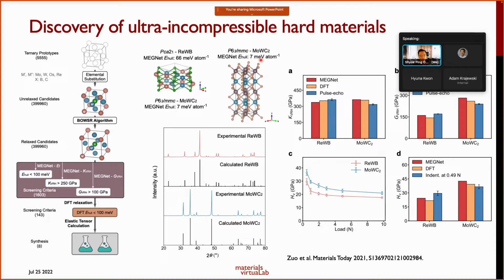Now, even with such a simple concept, we can already apply that to materials discovery. So I'm going to show you an example here, which is, I would say, one of the few examples where we apply machine learning to predict new materials, and we bring it all the way from prediction to actual synthesis to actual application, right? So the way that we did this was we chose ultra incompressible hard materials as our application field, and we started with about 5,000 ternary prototypes in the ICSD. We do combinatorial structure atomic substitutions on these 5,000 prototypes, and we generated about 400,000 unrelaxed candidates of different crystal structures that can potentially be interesting.